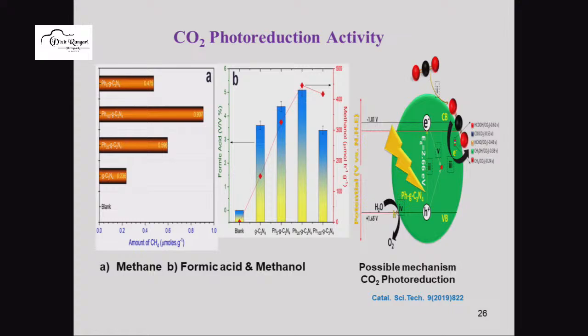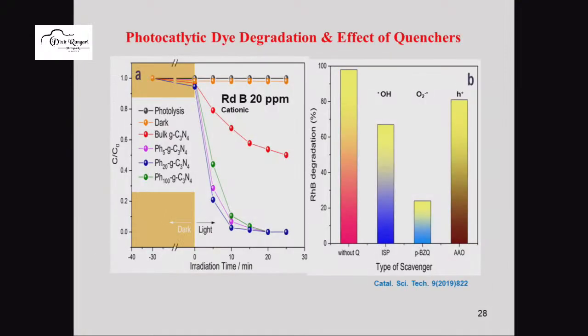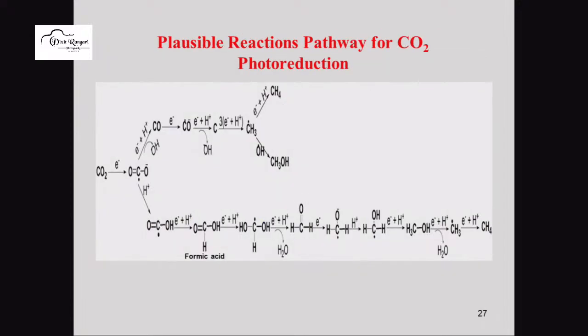The methanol, I think, is not much visible. There is a generation of methanol, formaldehyde, and methane, and this is the phenyl grafted g-C3N4. It shows more enhancement in the generation of methane as well as methanol and formic acid compared to graphitic carbon nitride. And scientifically one has to justify why there is an increase in the activity of a material after grafting, since there is an increase in the surface area and an increase in the lifespan of the material. And this is the proposed structure of how it can be formed. There is a formation of methane, methanol, and formic acid.